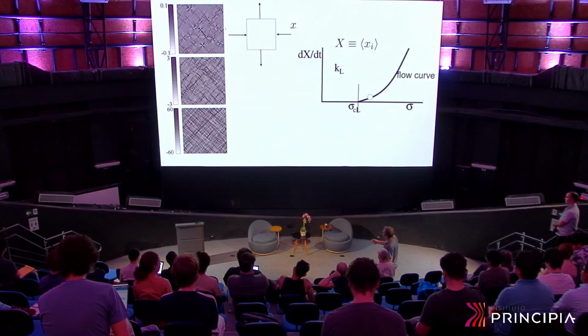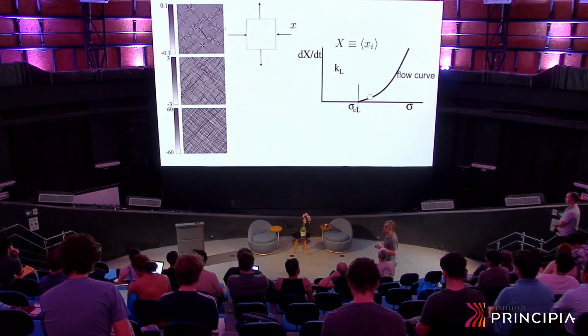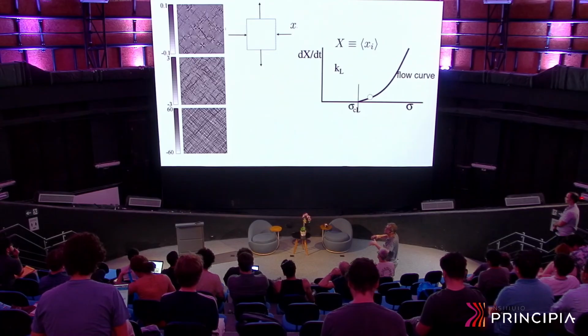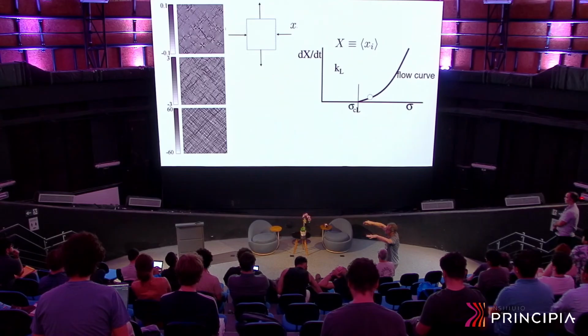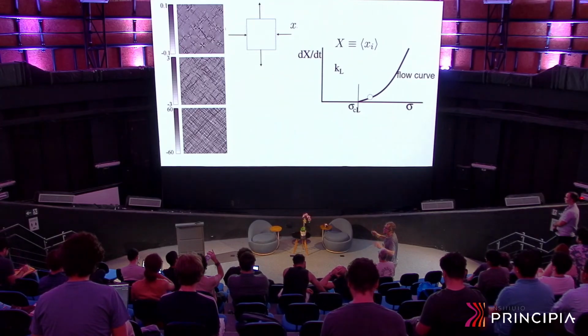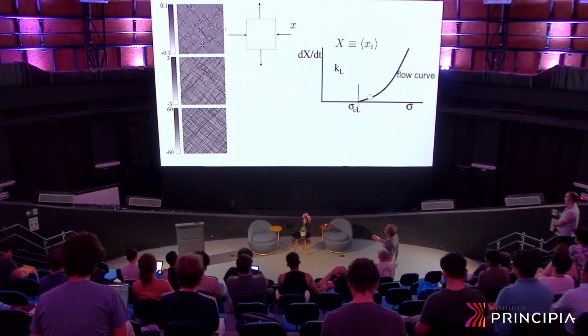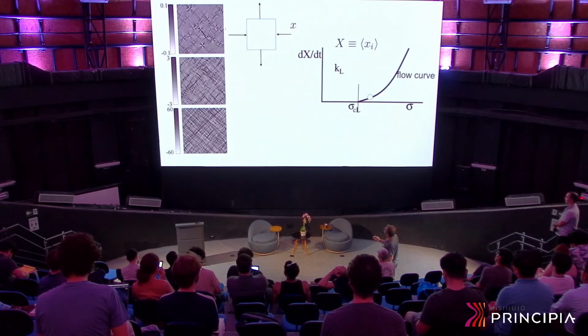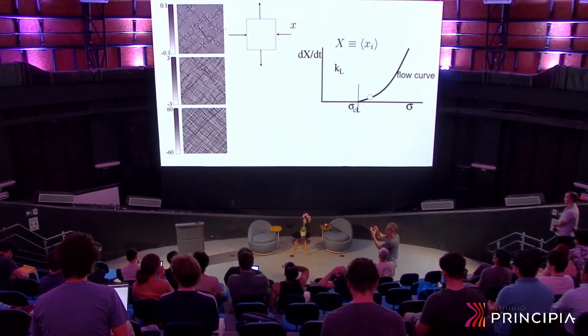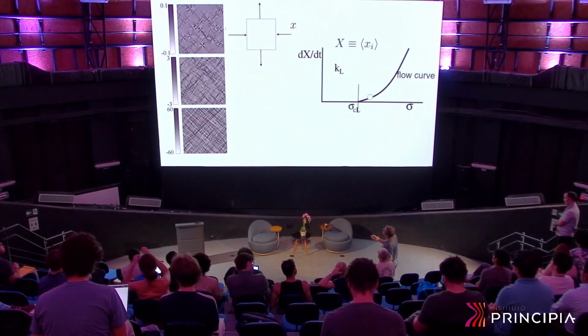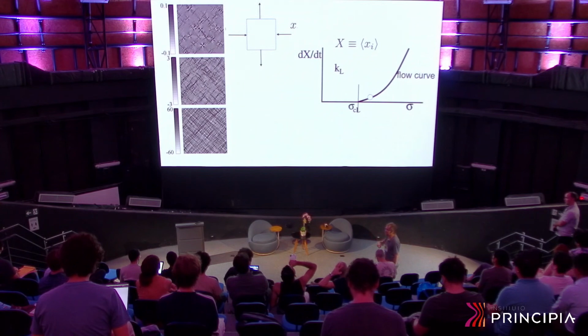But the idea of this plot is to show the heterogeneous strain deformation in the sample. If you average over a very long period of time, these heterogeneities average out in a very long simulation. But individual spots are very clearly seen when you do this. This corresponds to local rearrangements of particles that produce elastic interactions with this typical quadrupolar form. That is what is encoded in this SLB kernel that I mentioned. I don't know if this addresses your question.